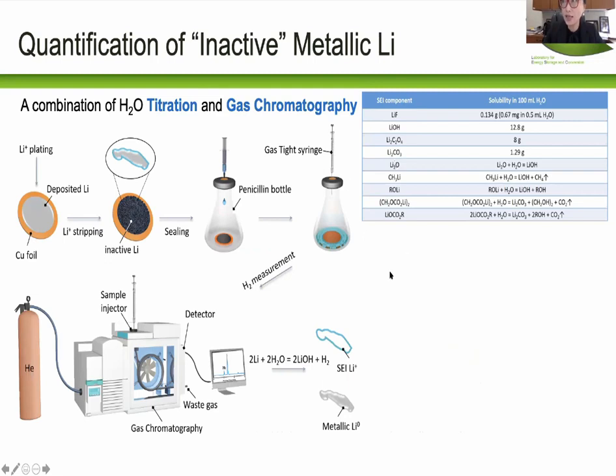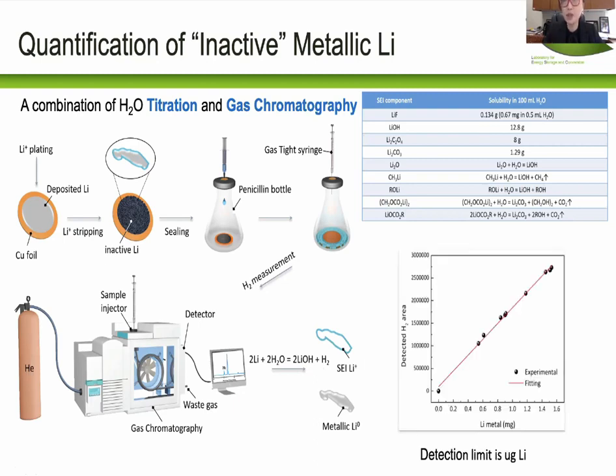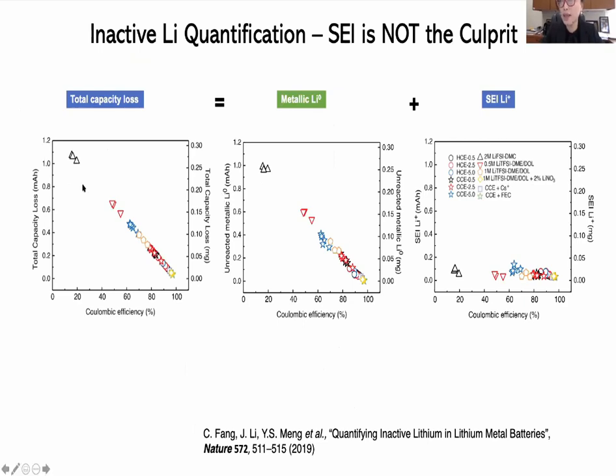So it turns out all the SEI components can dissolve or react with water to generate methane or CO2. Lithium metal is the component that will generate hydrogen. So we built something using titration gas chromatography to basically titrate out this metallic lithium and measure the amount of metallic lithium in whatever current collectors or substrate that you have. It turns out, after we used many different types of electrolyte, they all have different capacity loss, different coulombic efficiencies, we can actually see that the metallic lithium, the one encapsulated in the SEI, correlates perfectly with the capacity loss. Not the SEI; actually the SEI amount is almost identical. The composition and amount is almost identical.